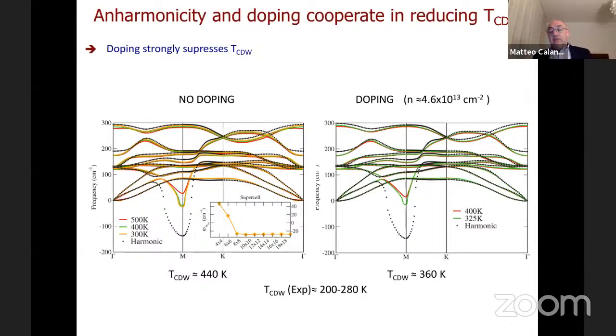What we are looking at when we look at the imaginary frequency is the atomic positions that are fixed and the phonon that is however unstable. So the temperature dependence in this case changes below the charge density wave temperature and becomes much weaker. And there is actually nothing that tells you that this temperature dependence should still be linear below, when the phonon has already become imaginary. This is why. Generally, what we see is that there is a small region of temperature where this is all constant, and then it decreases a bit more.